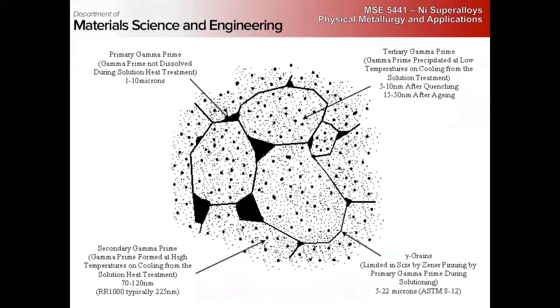So the general microstructure kind of looks like this. We have our large gamma grains, and then we have primary gamma prime grains. These are large grains on the order of 10 microns or so, which remain after the solution heat treatment, right? In some conditions we want them, other times we want to dissolve them completely away. Secondary gamma prime is going to form at high temperatures on cooling from the solution heat treatment. And these are tens to hundreds of nanometers, right?